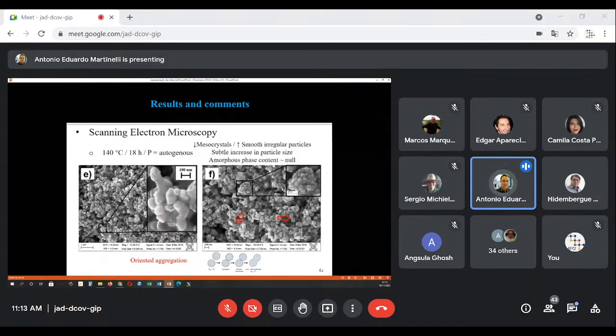140 degrees, 18 hours, autogenous pressure. We continue with the growth of the particles following the mechanism of oriented aggregation, as can be seen here on this neck formation in this picture. I always have to thank Armando for his patience, not only to build the reactor and synthesize the powder, but to obtain these, in my opinion, very nice pictures that show the sequence of events with temperature and time.